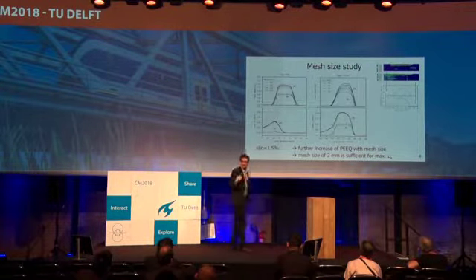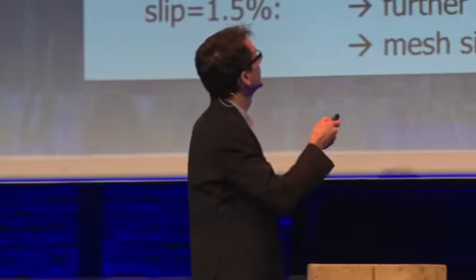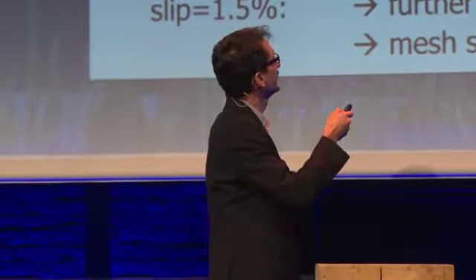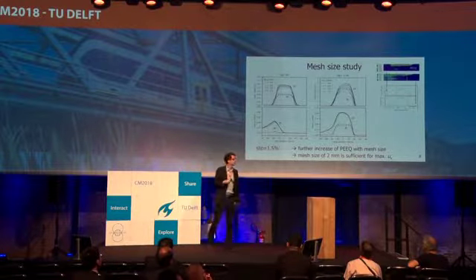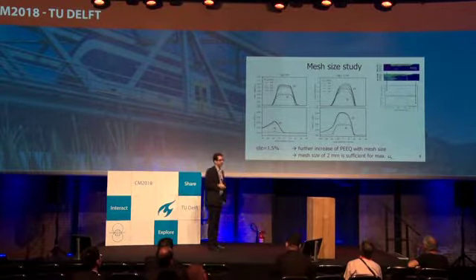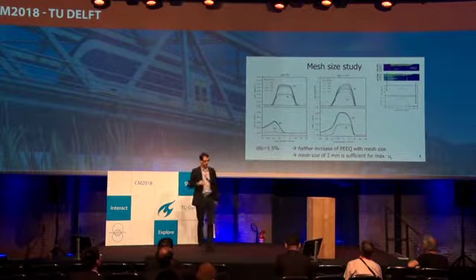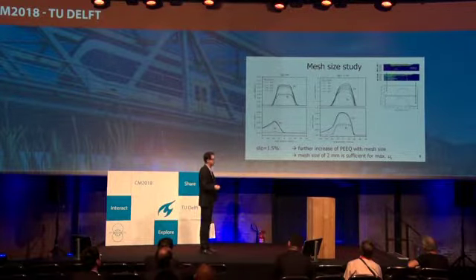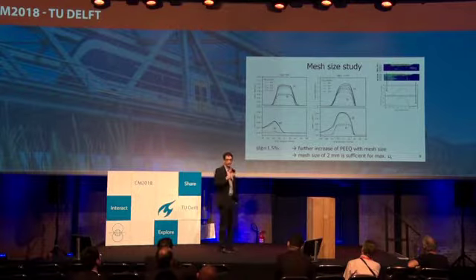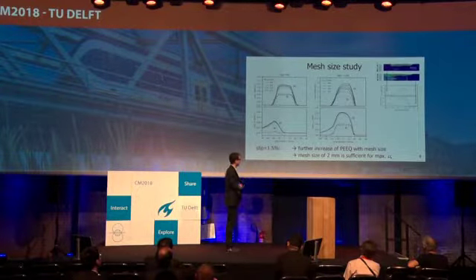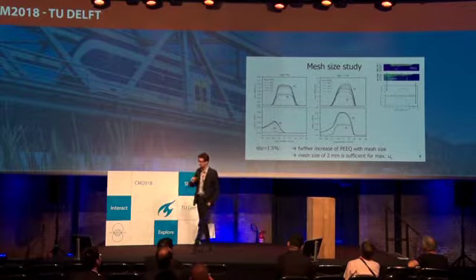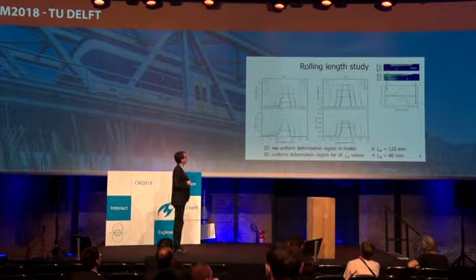For a slip, which is the more realistic and more relevant case, we see that our plastic deformations still increase with smaller element sizes. So we do not reach kind of a plateau or something there. But when we look at the displacements, which is really what interested us, it's already okay for 2 millimeter mesh size. So in that case, we say, the PEEQ would further increase. We're interested in the shear displacements, so that's fine if we take a mesh size of 2 millimeters. And now we proceed. The next question is, how about the rolling length?